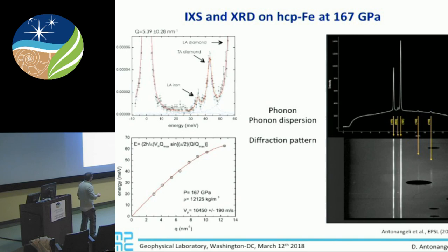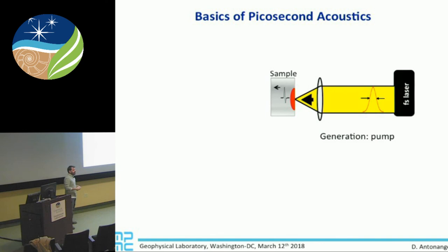This is important to have a clear phase assessment and density determination, but also to look at texture. These are the obtained data caked, unrolled around the beam to have one projection. It's important to observe that if these lines are not straight, if they start having some waving, this is an indication of plastic deformation. And the intensity should be as smooth as possible across the line, indicating that we are close to a random distribution of grain orientations. If we start having something very spotty, we are far from this random approximation. So clearly we are measuring something, but then the interpretation is not as straightforward.